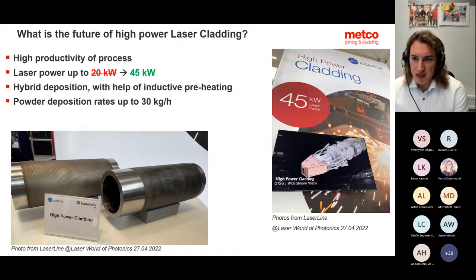We move forward. What is high power? If you had asked me 2 years ago, I would have said, yeah, I know a couple of lasers industrially working at 20 kilowatts, but the world is not standing still. We move forward. And this year in April, for example, Laserline introduced high power cladding concepts where they industrially sell 45 kilowatt lasers. There might be a discussion whether you need a 45 kilowatt laser in terms of production, but the fact is you can have it if you find a way to work with it, and the powder deposition rates going up to 30 kg per hour of material, in my opinion, is extremely impressive, especially if you think about hydraulic rods where you need a certain coating thickness, for example, 1 millimeter of Inconel. Covering this type of surface with a high power laser might give you a lot of economic advantages.